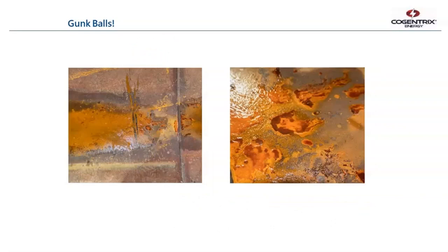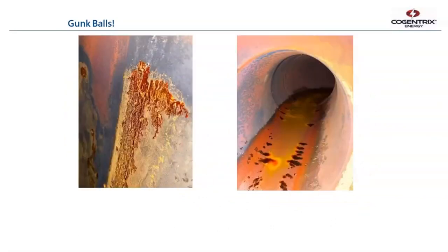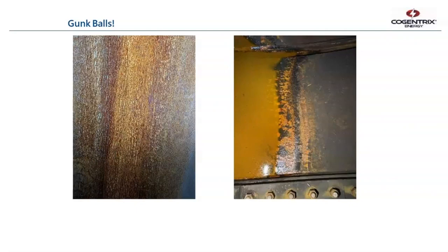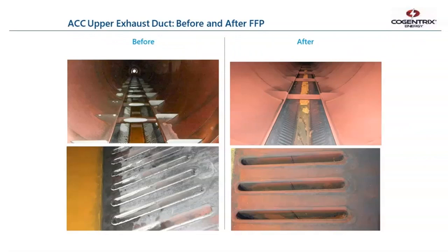More close-ups of what the gunk balls look like in our turbine. This is all puddles on the floor. You can see there are globules starting to form pretty much everywhere where water was running down. You see these bright red streaks. The picture on the right is where the pump suction is taking off. It's usually pretty dry. More pictures of the streaks running down everywhere that the water touches. So that's the gunk ball, and that was the deciding factor with the gunk ball.